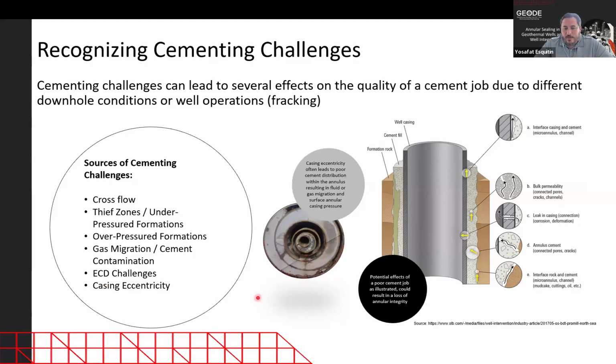the casing eccentricity. So you see on this picture here, this was an offshore well where a section of the casing was pulled out of the well, and you can see that in different annuli, there's basically no cement or very bad cement quality in some sections. You can see on the very last one here, this eccentricity of the casing creates this unremovable mud when you're pumping the cement that doesn't allow it to be displaced out, and then you have this whole channel for gas migration or potential fluid migration. So eccentricity plays a big role.